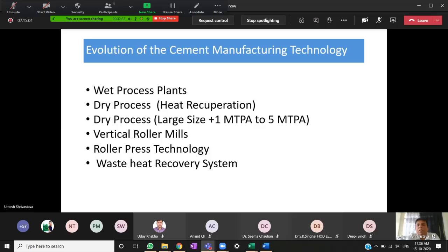Then that powder has to be heated to a very high degree, something like 1400 to 1500 degrees Celsius. At that temperature, the powdered limestone fuses and forms a clinker, and that clinker is the intermediate product of the cement. Now that clinker is further ground to make the cement. So the whole process is all about grinding, heating, and again grinding, and maybe mixing and then transportation.